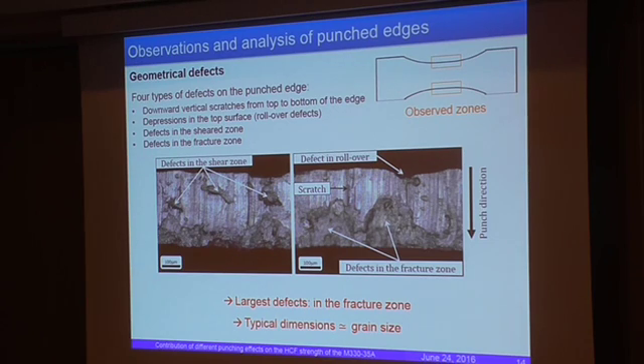We also looked at the geometrical defects. If we look at the edge, you see that there are pretty large defects. So you find vertical scratches, but also depressions in the top surface, defects in the shear zone, but the biggest defects are located in the fracture zone. And all cracks initiate on these big defects in the fracture zone, which are about the size of 2 grains. So we assume that during the punching process, we get some grain decohesion leading to this geometrical defect.